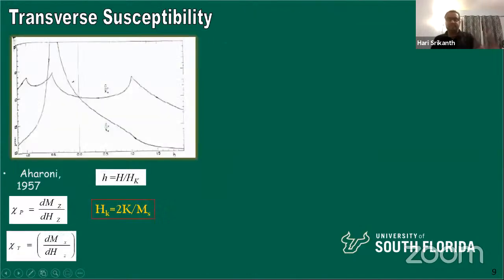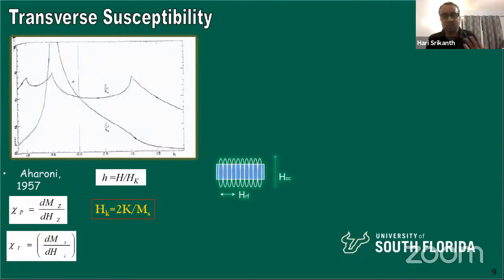And again, there's a very famous paper by Aharoni, who's a well-known theorist in the field of magnetism. He had predicted that for single domain nanoparticles, you can actually see these sharp peaks. He calculated the transverse component of the susceptibility, and he showed that these peaks can occur exactly at the anisotropy field. So if we can do these experiments, exactly what we did. What we did was we actually confirmed Aharoni's theoretical model, 40 or 50 years after he proposed it.